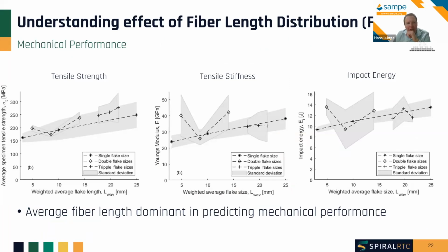And without going into too much detail, what we see is that if you look at strength, stiffness, and impact energy, although there's some variation, obviously, what we feel is that the average fiber length is dominant in predicting the mechanical performance. Which is in principle a good conclusion, that even if there's a distribution of shorter and longer fibers, you can still go to a predictable performance. So these are initial results, and we're looking further into this. But this is, let's say, first results, which I would like to present.